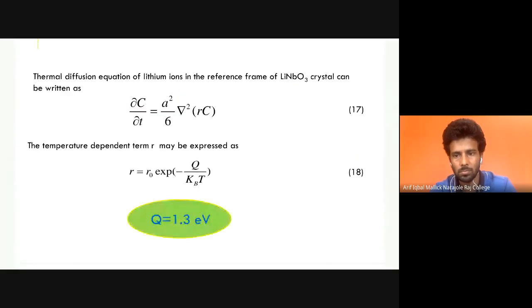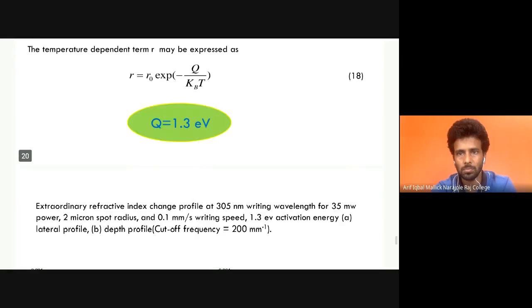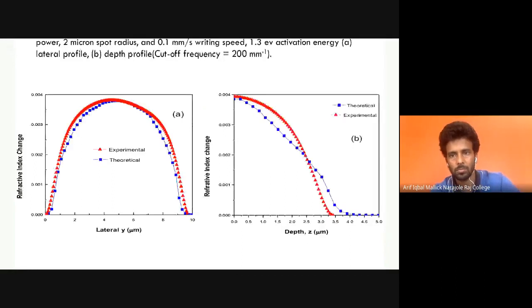In the thermal diffusion equation, there is one term R. R can be written as R0 e to the power minus Q by kT, where Q is the activation energy. Now we optimize Q to 1.3 eV, which explains the actual refractive index profile. The red curve is the experimental result, and the blue curve is the theoretical result, which agrees fairly well. So our model explains the formation of the UV written waveguide at 305 nanometer writing wavelength.